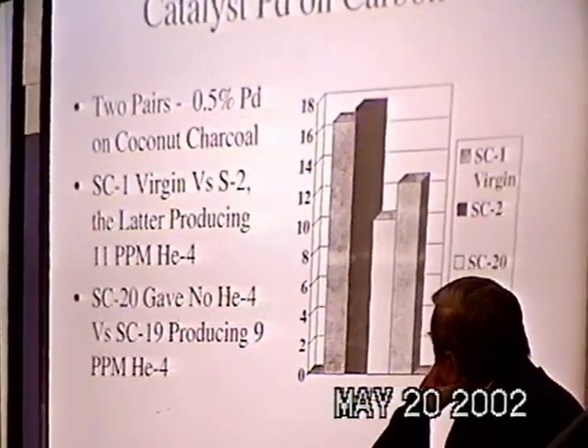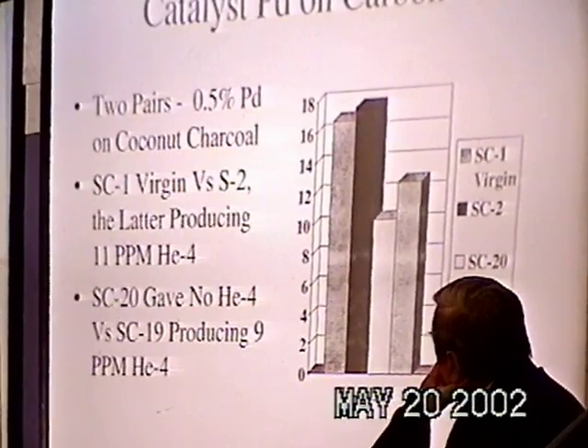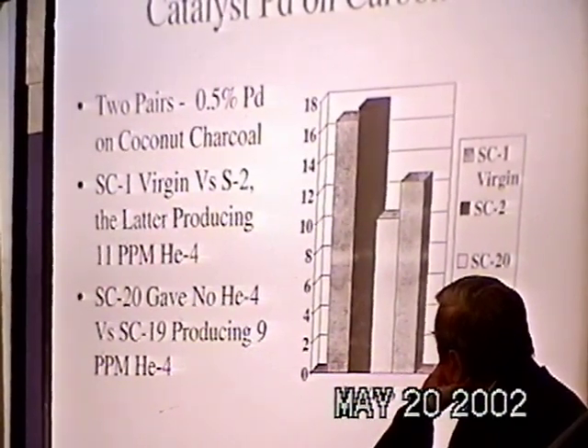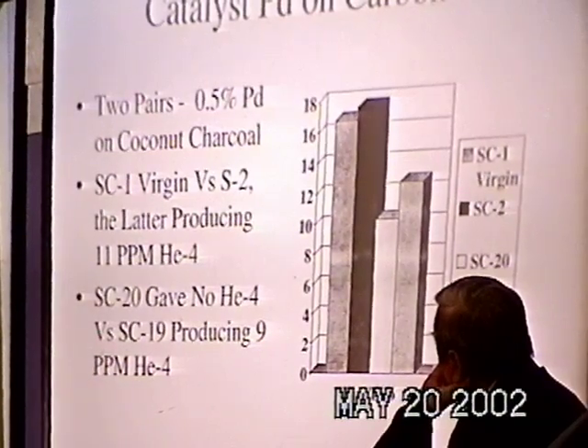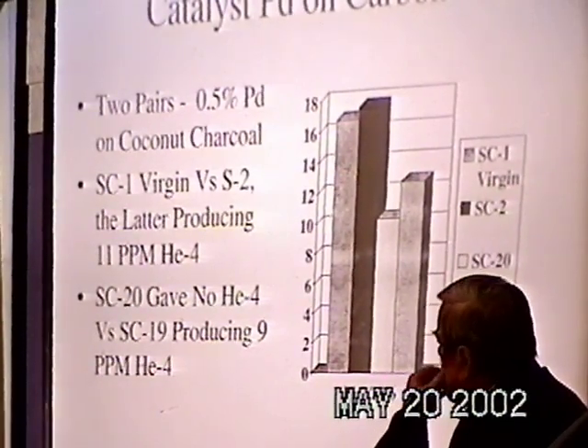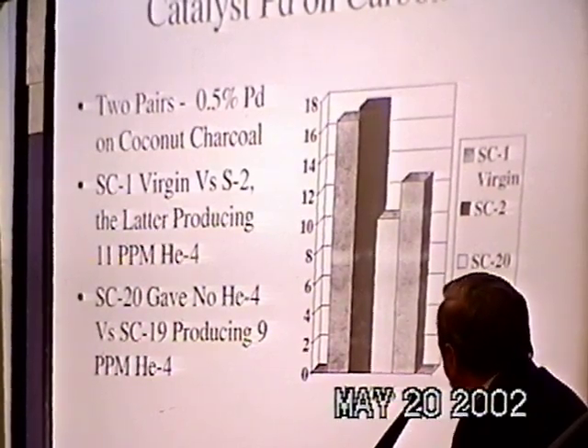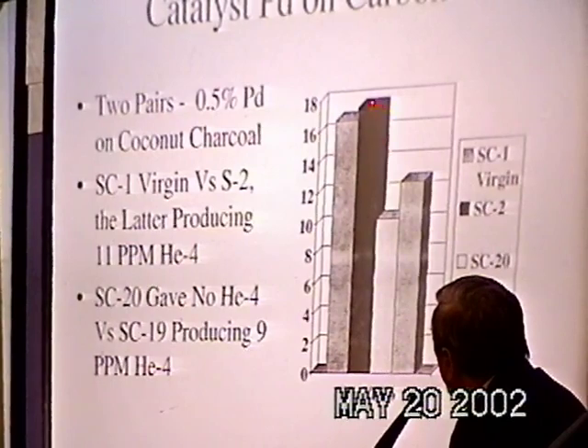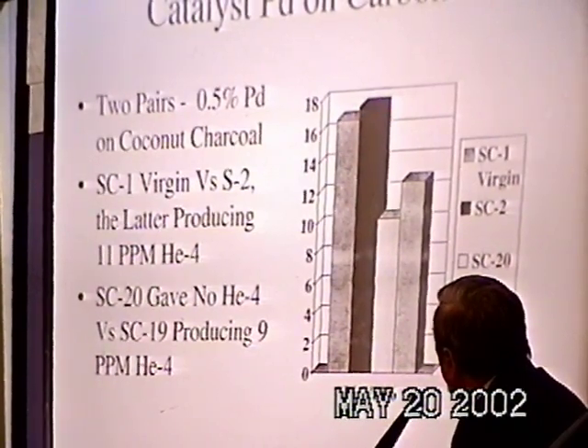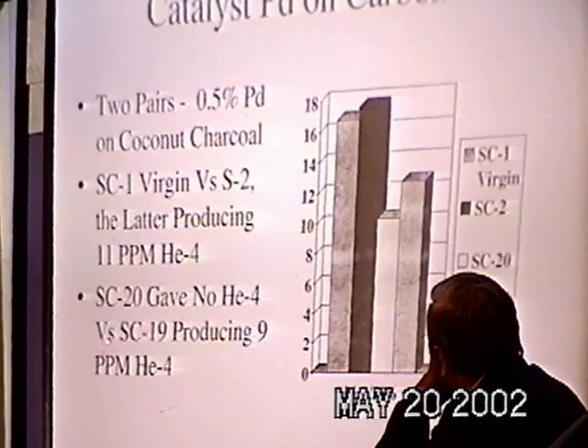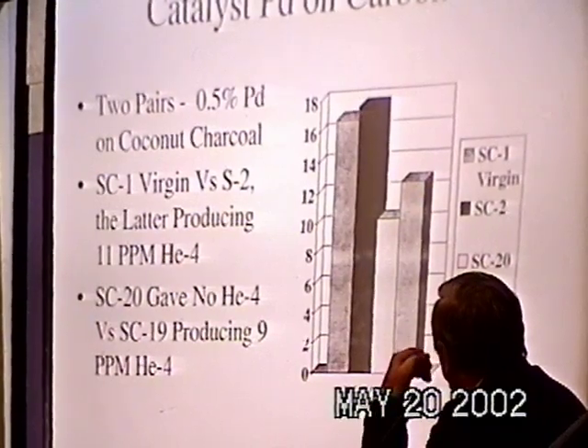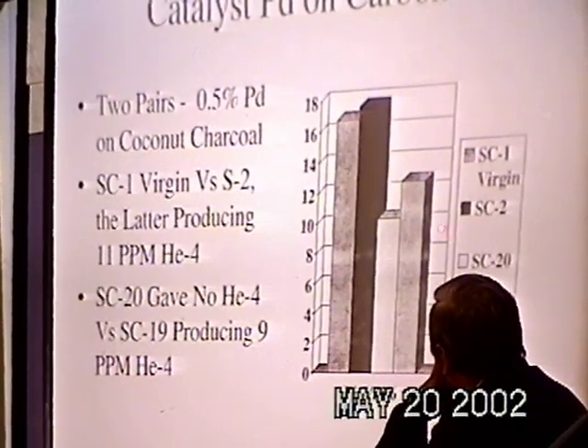Here's the catalyst of palladium, similar to that which Lester Case had introduced: 0.5% palladium on coconut charcoal. And here we have SC1, the virgin material. And here's SC2, which had produced 11 parts per million of helium-4. You can see it's not impressive, but it is positive. And then we had the SC20, which gave no helium, versus SC19, which gave 9 parts per million helium. And we see a rather well above the limits of error increase in the active sample versus the one that didn't produce any helium.